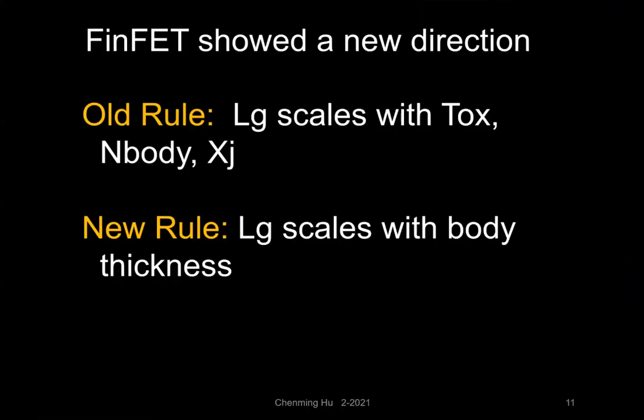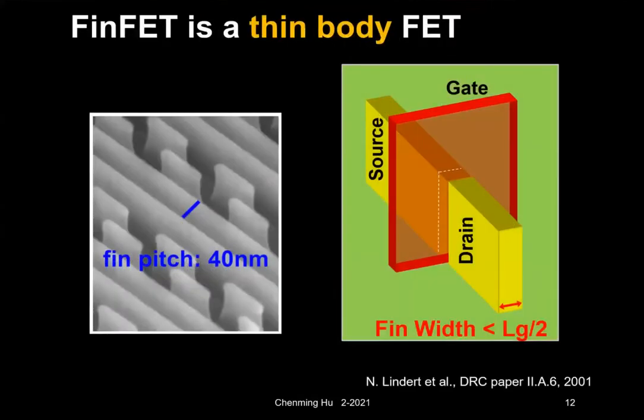So I will not go into the physics of that. I think most of you already know why FinFET can overcome all that. But the important thing is that FinFET showed a new direction. The old rule was that LG scales with TOX, body doping concentration, and junction depth. The new rule says that LG scales with the body thickness. In other words, what really is important is to think of FinFET as a thin body device. This is the body, yellow is the body. You just have to make the body very thin. If you can make the body thin, you can continue to reduce the gate length, and you don't have to really reduce the oxide thickness.